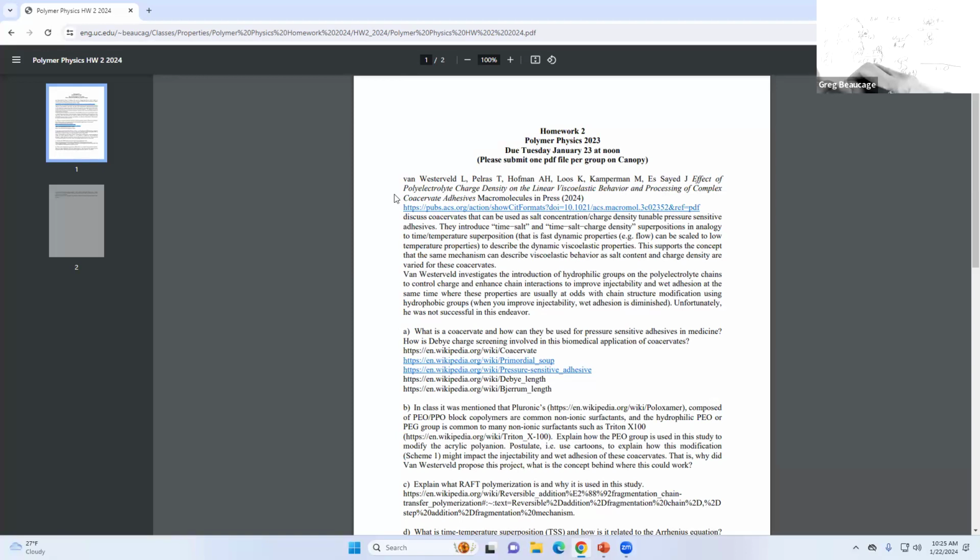And in the WLF, which is the standard format for viscoelastic time temperature superposition, you're going to do a frequency measurement where you're oscillating the plate, at room temperature. And then you're going to do it at 100 degrees C and at like minus 50 degrees C. Those 3 curves would be like that curve for G prime, maybe here and then there, right? So you want to get those all to overlap with each other, or they'll be different parts of the same curve.